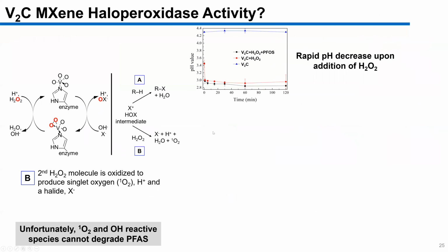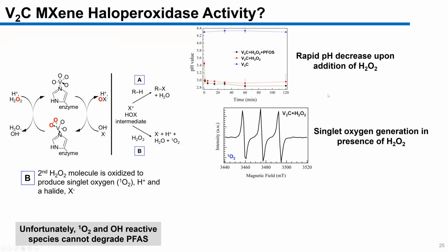Sorry about that. So first, to indirectly verify that this was happening, this B pathway suggests that protons are released. So in that case, the pH should decrease if you add hydrogen peroxide, and we observe that in our reaction system. This blue curve is just V2C and water, and then the red and black curves are V2C and hydrogen peroxide. Once you add that hydrogen peroxide and or PFAS, you get a rapid pH decrease. So that was one indirect measure. The second indirect measure was the formation of singlet oxygen when you add hydrogen peroxide, and also when you don't have hydrogen peroxide, which was an interesting finding for us too.